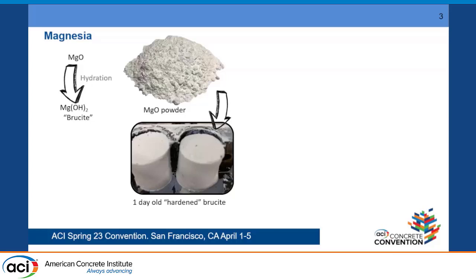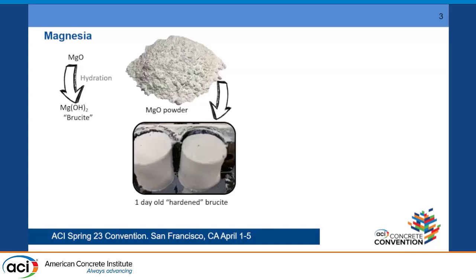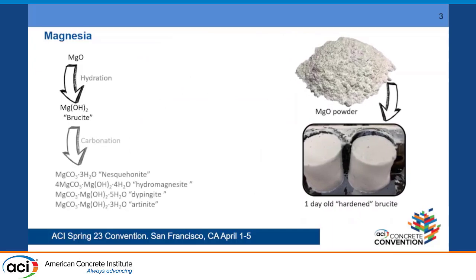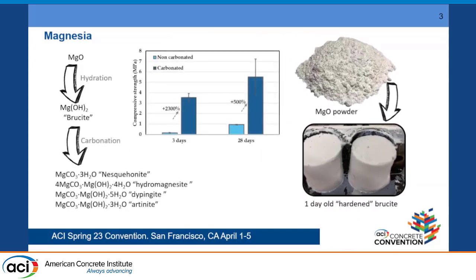However, we don't use it as the main binder, simply because it's weak. This is how it looks after you cast it for 1 day. This is technically hardened, and it can barely sustain its own weight. And this is typically why it's not used as the main binder. However, magnesium has a trick. Once it hydrates, it can actually carbonate. And when it's carbonated, we can see that it can gain a lot of physical strength.